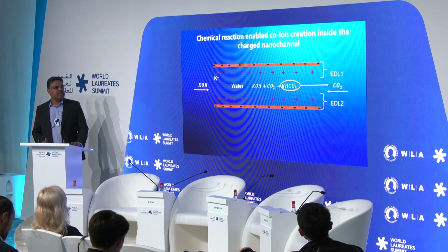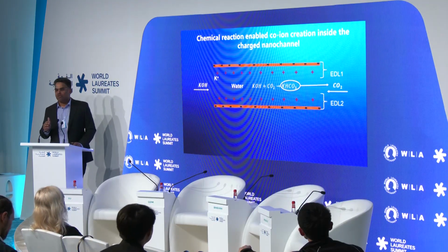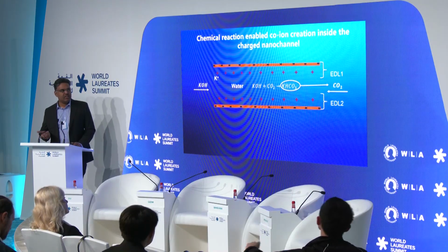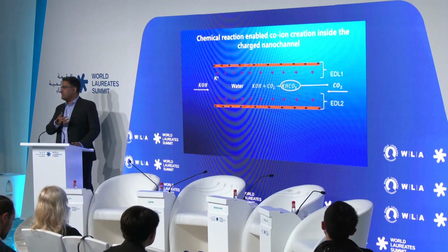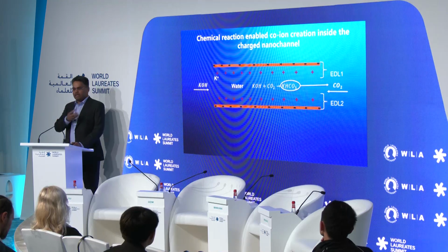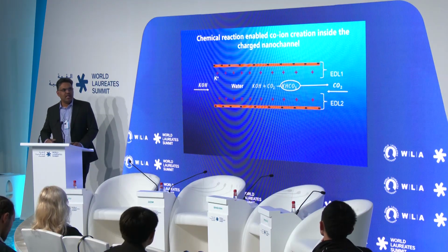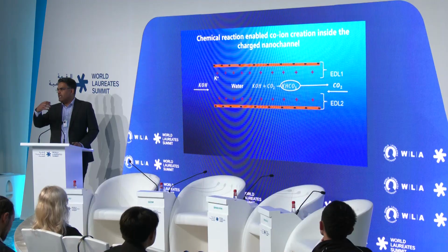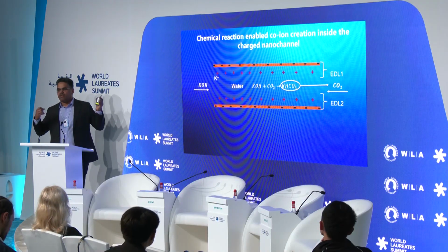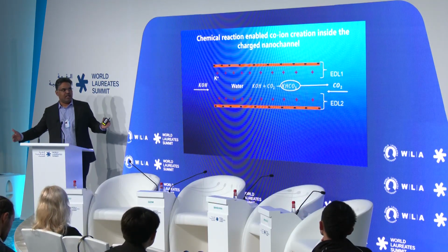This is what exactly we did in the experiment. We take a graphene oxide membrane, which is negatively charged, and on one side of the membrane we take an alkaline solution, like we add some potassium hydroxide or ammonium hydroxide. On the other side of the membrane we added carbon dioxide gas. So one side of the membrane is alkaline water, the other side is carbon dioxide.